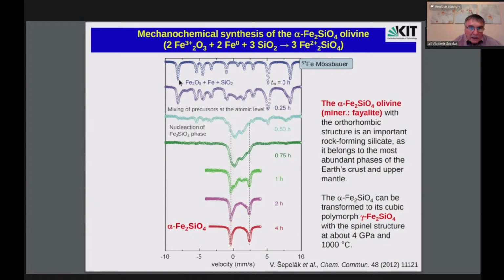nanocrystalline olivine, and from Mössbauer spectra we can even determine various stages of this process, like mixing of precursors at the atomic level. Then here is a nucleation of the Fe2SiO4 phase after half an hour, very quick. As you know, nature synthesizes this material over very long times, many millions of years, and we are able to do it in half an hour in our reactors. And you see the progress after 4 hours of milling, we have no traces of precursors, and the mechanosynthesis of olivine is complete.